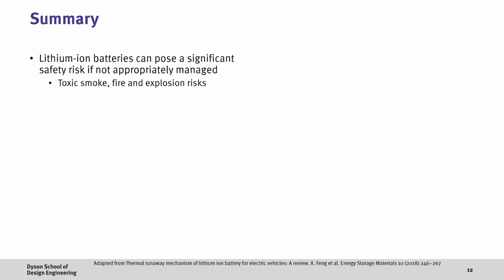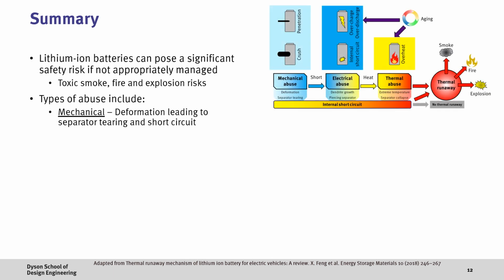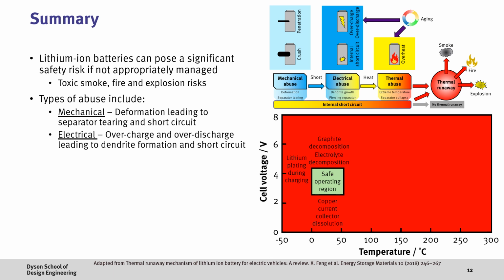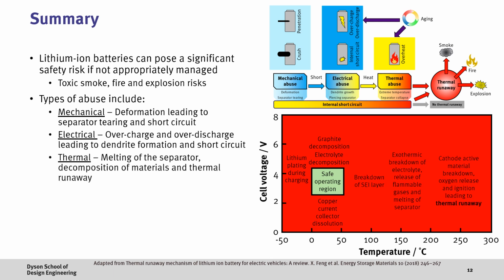So, to summarize, lithium-ion batteries can pose significant risk if not properly managed, with consequences such as toxic smoke, fire, and explosion. Types of abuse which can cause this include mechanical piercing or deformation, which can tear the separator leading to short circuits. Electrical abuse in the form of overcharge and over-discharge, where we can form lithium dendrites on overcharge as well as electrolyte decomposition, and on over-discharge we can dissolve the copper current collector, forming copper dendrites. And finally we have thermal abuse, which results in melting of the separator, decomposition of various battery components, and thermal runaway. The challenge in managing these factors are then compounded when the battery is aged.